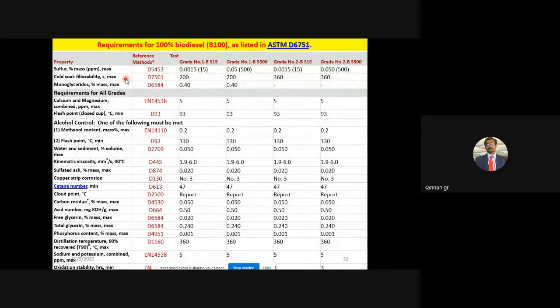For example, the temperature keeps on decreasing, and at the same time they pass the biodiesel through filter paper. Then they find how many seconds it takes to pass through this filter. The maximum limit is 200 seconds. Then it will pass these conditions. Similarly, the sulfur present in Grade 1 biodiesel is 15 ppm, that means 0.0015. Grade 2 means 0.05. Sorry, Grade 1 BS500 means 0.05. Then Grade 2 has the same values.